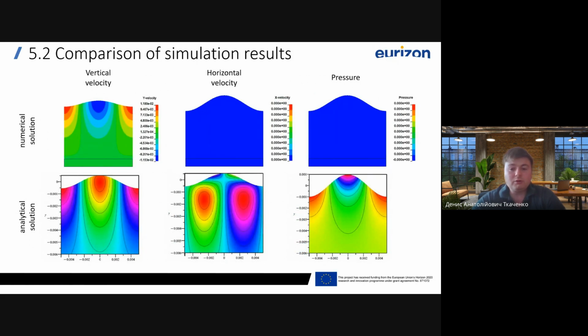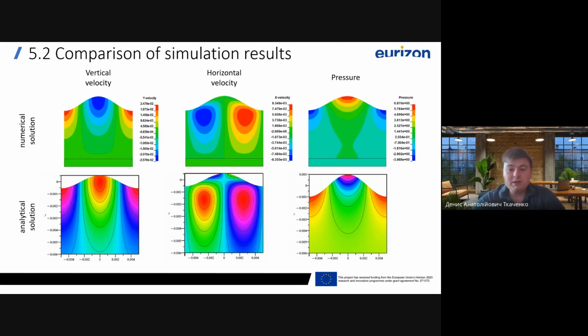Amplitude evolution over time was also compared to assess the analytical model's accuracy. The focus was on the simplification introduced at the upper boundary, applying the boundary condition at z equal 0 rather than at the free surface coordinate, using simplified stress components and neglecting the curvature denominator. These are absent in the numerical model, which solves the full system.